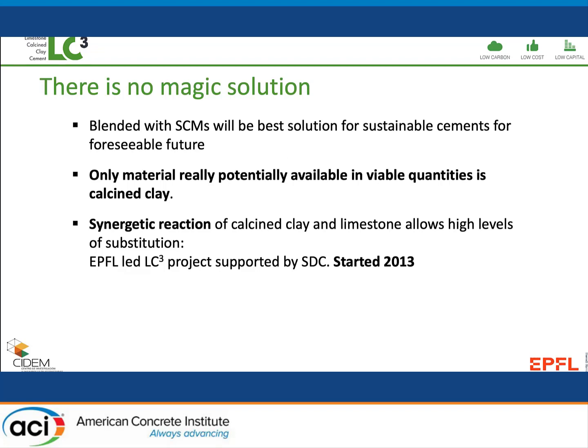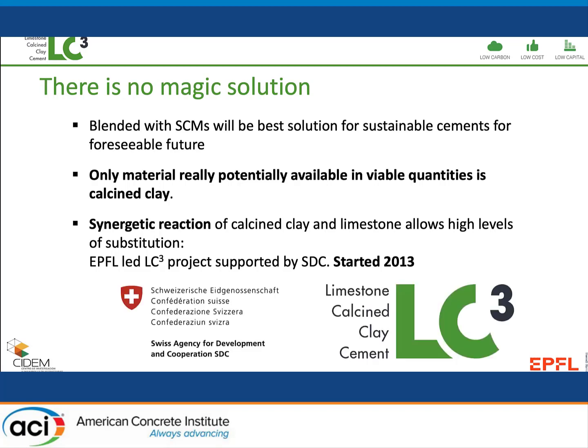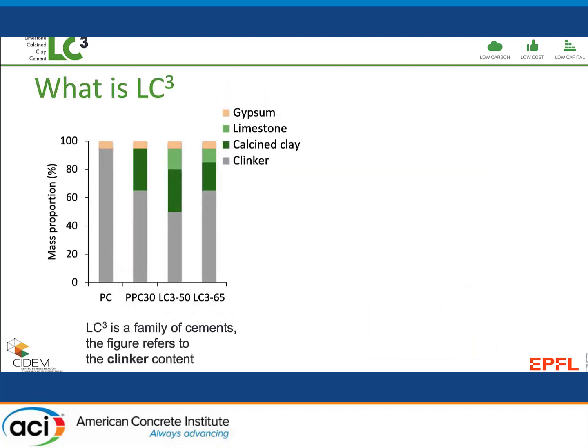What is really, really interesting is this synergistic reaction between calcined clay and limestone, which can allow you to go to high levels of substitution, which is behind the technology we call LC3. And basically what LC3 is, you use this combination of calcined clay and limestone, a bit like what Jesper showed, and you can have very different levels of addition. So Jesper was talking about LC3-65, basically, which would be allowed under the past European standard.